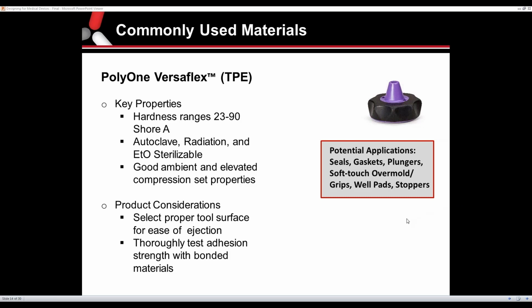And there are different TPEs that work with different substrate materials. A lot of times in the design process, for your substrate part, it's always important, when you can, to mold in features that will allow the overmold material to embed itself within the substrate, whether that be some small mechanical locks and things like that. So that's very important, just to aid with the adhesion.